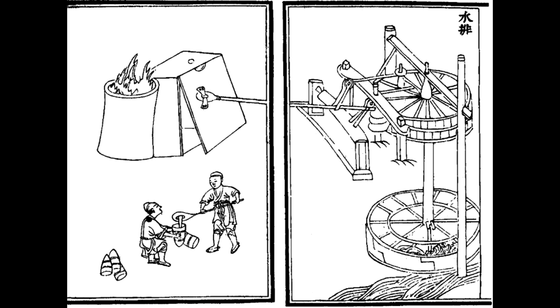Craddock, original citation, 269. Given that the process of malleabilization often required keeping the iron hot in the open air for hours, if not days, and given the fuel demands, it is not surprising that sometimes lower quality metal was produced by cutting the process short. By the 1st century BC, Chinese methods of malleabilization clearly improved, with solid-state decarburization becoming reliable enough in producing steel and iron from cast iron that bloomery smelting was abandoned in favor of it.